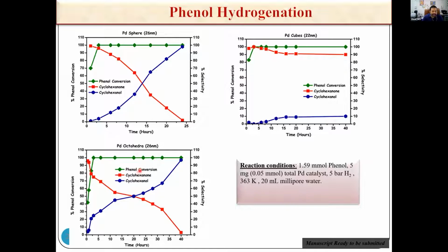If you take palladium spheres, as I mentioned in my previous slide, a palladium sphere carries 111 and 100 planes, 70% of 111 and 30% of 100. Whereas if you take palladium octahedra, which carries only the 111 surface exclusively, you again see a similar trend like the palladium sphere. So you get 100% conversion, and once you carry out the reaction for an extended period of time, the cyclohexanone goes down and cyclohexanol starts to grow, and it reaches 100% selectivity after a certain period of time.